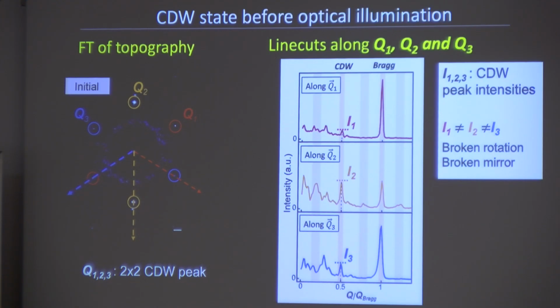charge density wave peak. But in any case, it does tell you, if you take this seriously, that two symmetries are broken. One is rotational symmetry, because this peak and this peak, Q1 and Q3, this peak and this peak, Q1 and Q2, don't have the same intensity. And actually, it's not surprising that one of the three should have a different intensity, because this is a 3D CDW. If you look at one layer, the layer underneath it, the CDW is shifted in one direction, okay? It's staggered, in an alternating way. So because of that, one direction is picked by the system, so one of the CDWs can be a different intensity. So rotational symmetry is broken, that's okay.